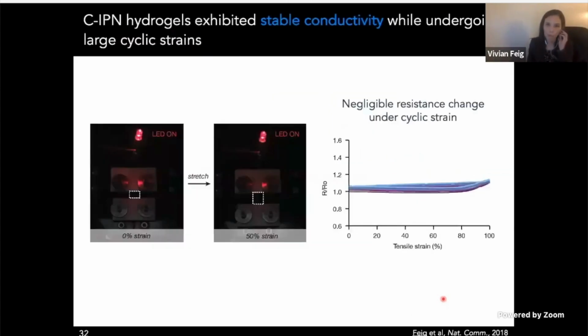Also important is that these CIPN gels have stable conductivities with strain. So here we see that the electrical resistance across the gel stays pretty constant even when cycling back and forth between 0 and 100% strain for 10 cycles. And we think that's because there's a lot of water embedded in these materials, meaning there's a lot of free volume for the polymer chains to be able to accommodate strain without having to actually break down the conductive network.